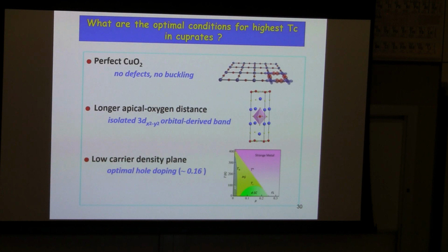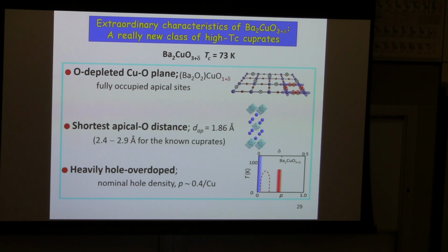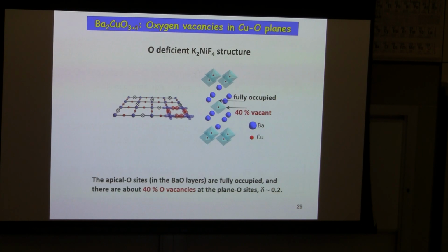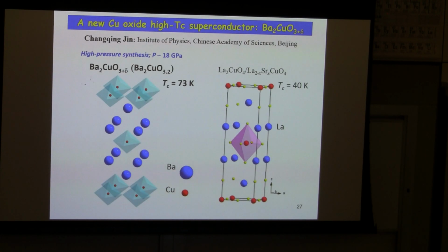Although the TC at the moment is only 73 K, it should be compared with the almost nearly isostructure lanthanum 214. In the case of lanthanum 214, TC only has 40K. It's almost a factor of 2 higher in this simple chemical formula compound.